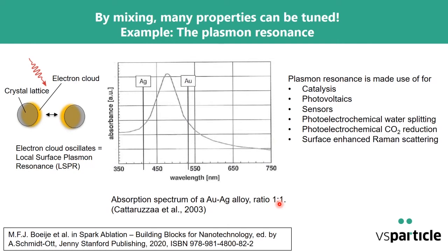And because mixing is easy using the spark, you can produce particles with any plasmon resonance that you want. By the way, it's also size dependent, so you can also use size to adjust the plasmon resonance frequency. And this has a lot of applications that I listed here, from catalysis, photovoltaic sensors, to photoelectrochemical splitting of water or CO2 reduction. And a very interesting one, which I will also refer to in a little more detail, is surface-enhanced Raman scattering.